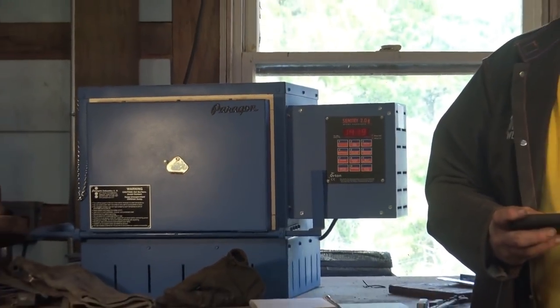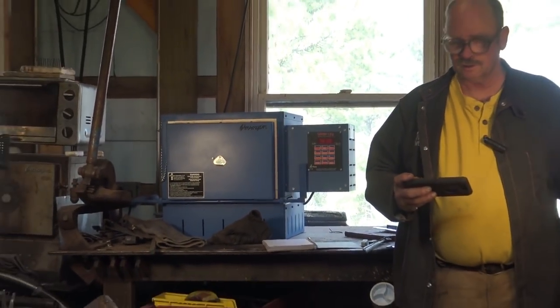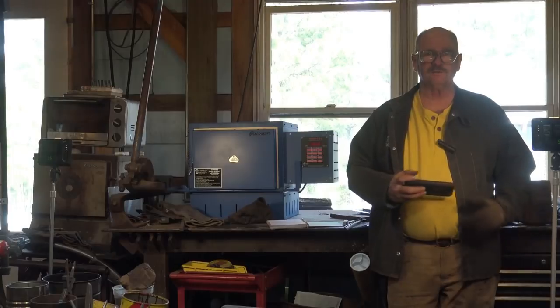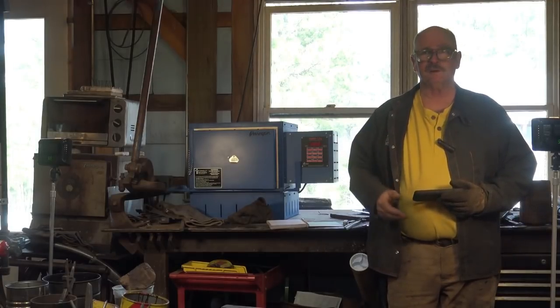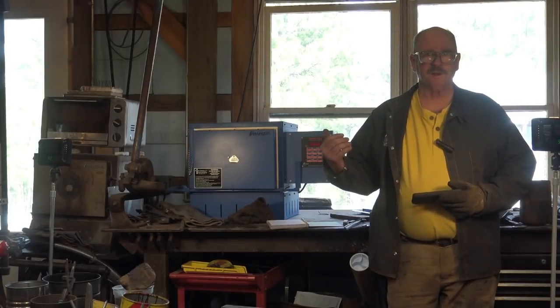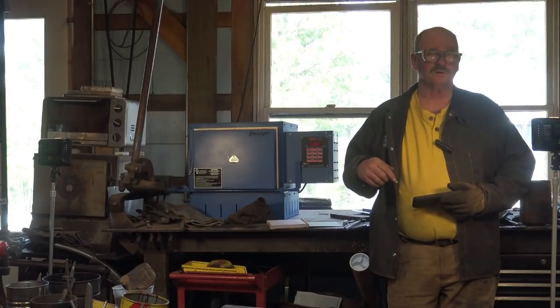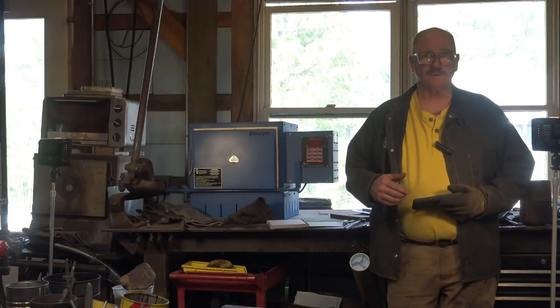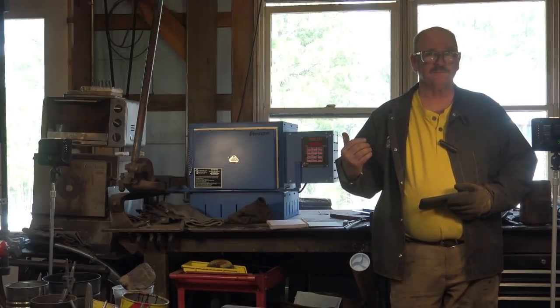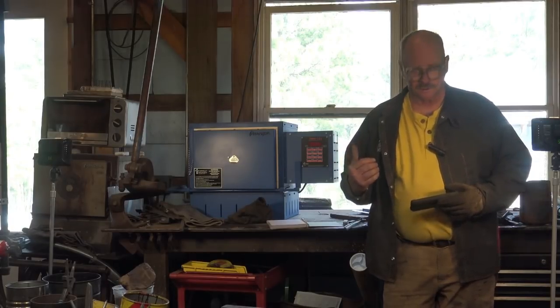Well, we have reached our target temperature on the oven at 1400 degrees. It goes up and down a little bit to try and maintain that temperature, but it's been here now for about a minute, and this is 75 degrees cooler than what W1 typically uses as a critical temperature. 1475 is correct. So let's see if it's still magnetic at 1400 degrees.